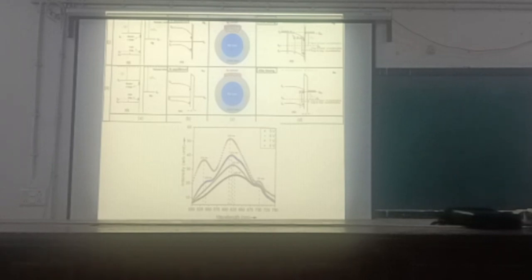Now to check this framework that we are proposing, we performed another experiment. We took gold and applied higher voltage. With the lower voltage we didn't get 3 peaks in gold, but when we apply more voltage, in gold also we get 3 peaks. That means we are probably in the correct direction. In this way you can control the color of the emission by controlling the voltage.